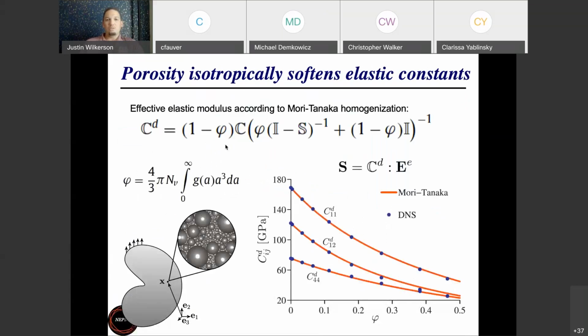Okay, so like I mentioned, voids create a porosity. Porosity is what we'll denote as phi here, and that's just the void volume fraction. So the number of voids that I have per unit volume of material multiplied by the total volume of all those voids, which is taken care of by this integral in 4/3 pi. And that gives me a net porosity in the material.